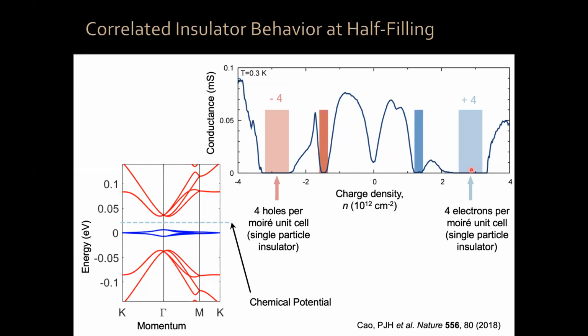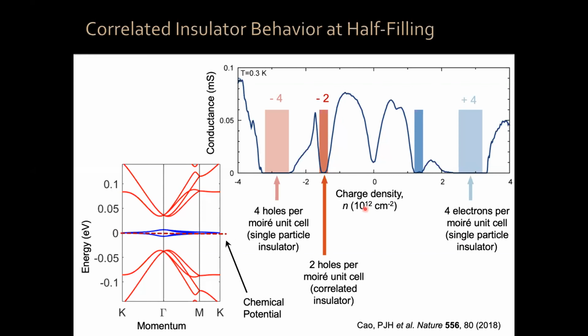Now, the funny thing is that if we put now our chemical potential, our Fermi energy, here in the middle of the valence band, the Fermi energy is crossing this band. We should have a good metal in there. However, when we put 2 holes per moire unit cell, we have an insulator. This turns out to be actually a correlated insulator, okay, as I mentioned earlier. If we shift the Fermi energy to put it in the middle of the flat conduction band, we also see an insulating state. This is at 2 electrons per moire unit cell, another correlated insulating state.